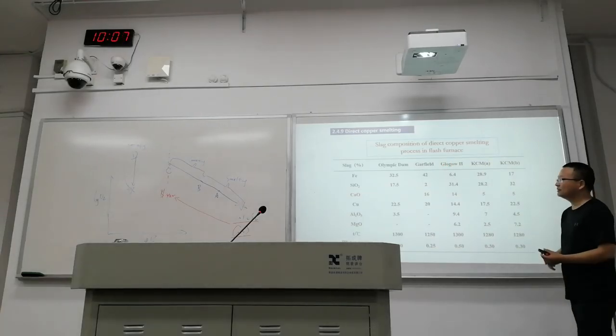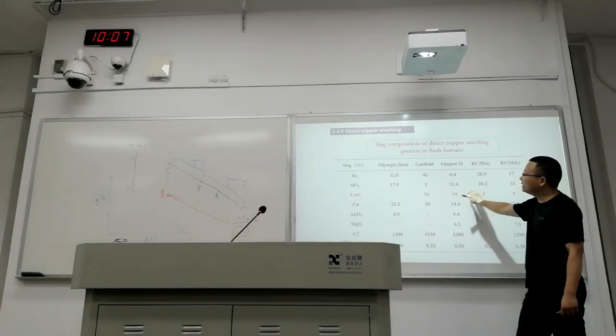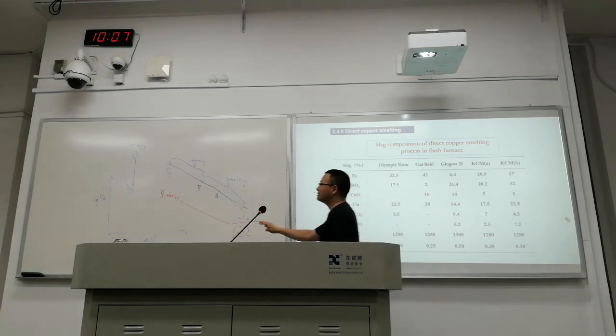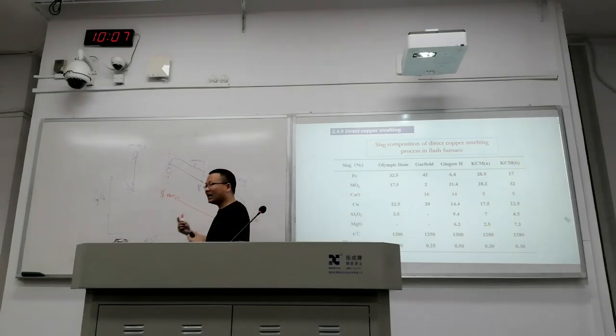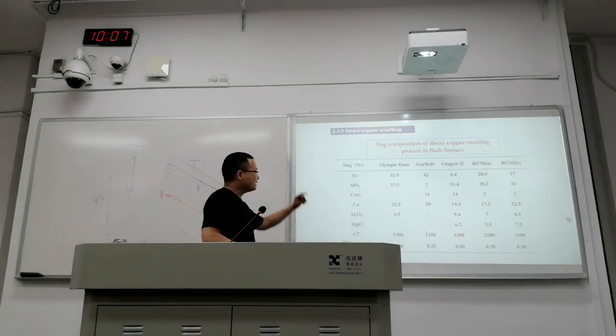So they are using one direct blister copper smelting technology. And in their furnace, as I have been mentioning, there are 2 layers. The bottom layer is blister. This is fixed. So this is the name, direct to blister copper. So DB, B is blister at the bottom. And at the top layer, the slag.